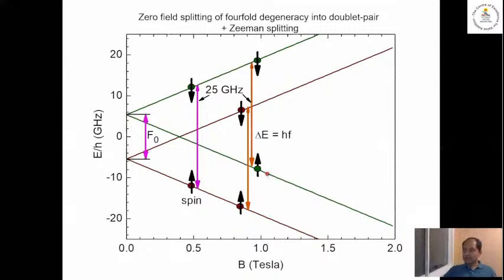So we saw 2 kinds of resonances, right? We saw the resonance associated with the orange line, and we're going to say that's related to our usual kind of spin resonance. But now it can be spin resonance between these brown lines, or it can be spin resonance between the green lines, right? That's flipping the spin due to photoexcitation by microwaves. And this kind of spin resonance has this usual property, which is that the splitting goes to 0 as you go to 0 magnetic field.